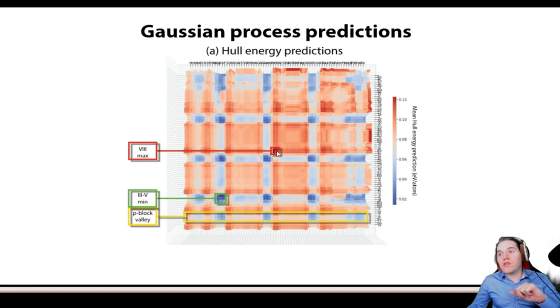The most red regions are things like noble gases, which don't really like to bond with anything, or atoms which are just incredibly big and completely destroy your crystal. The lowest energy ones are, of course, things like silicon itself and the elements which are very similar to it, which are very near in the periodic table. And you really see this behavior reoccurring as you go through the periodic table. This means that you are going down a column of the periodic table and seeing the same behavior. And this smooth and clean behavior is very interesting, because we create this surface with only about 10% of the data. So this shows that the model makes quite good predictions.